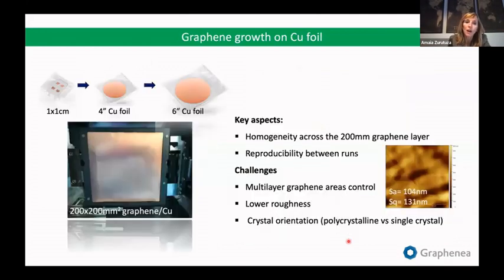Okay, we have experienced an evolution on the size of samples that we were growing. Of course, in these almost 14 years, that gives you time to develop the product, the growth, the transfer, and so on. You can see here how we started with really small samples, then we moved to 4 inches, which is like 100 millimeters, then to 150 millimeters, and now we are at 200, which is the relevant scale for many industrial applications in the semiconductor industry.